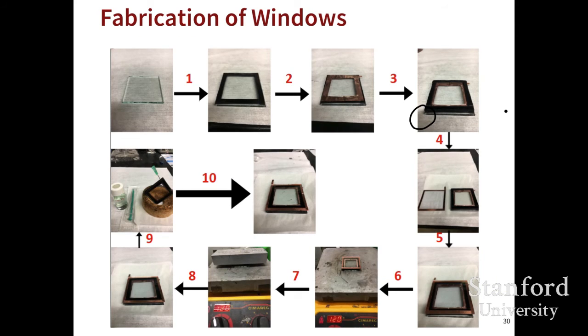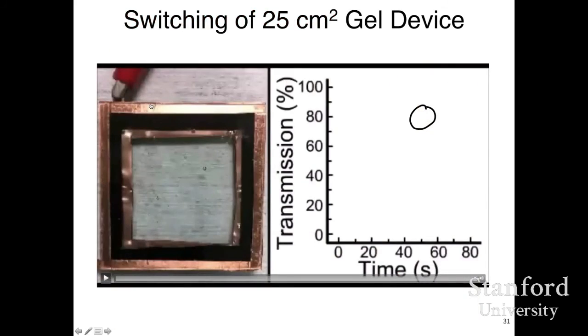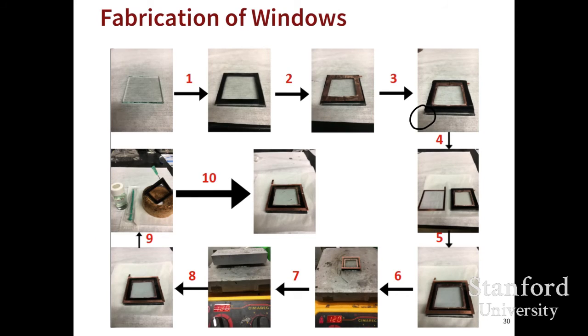Here you can see all the steps we use to make a window. We start with a piece of glass that you can see in the first box, and then we put a butyl rubber edge seal around there. It's probably not optimized yet, but it's something we just happen to have in our lab for packaging solar cells. And then we put copper tape around there, and that's going to be the counter electrode. For a window this size, we don't need a fine grid of copper throughout the window. And then we're putting on some more rubber edge seal over that.